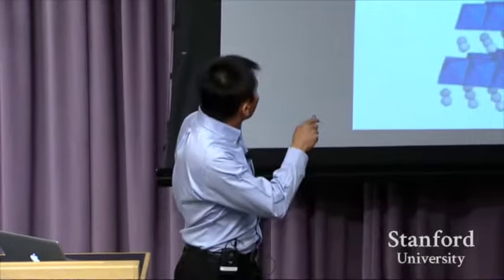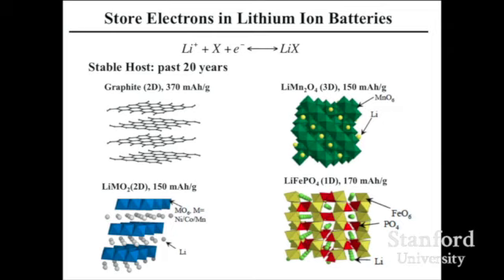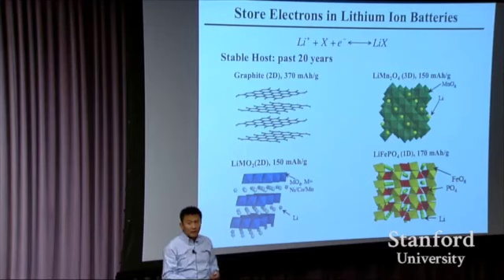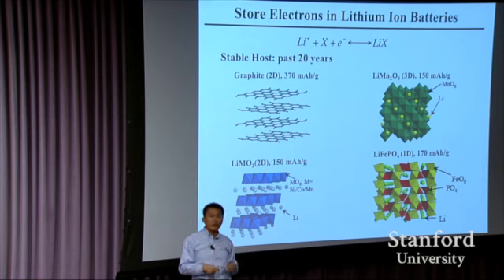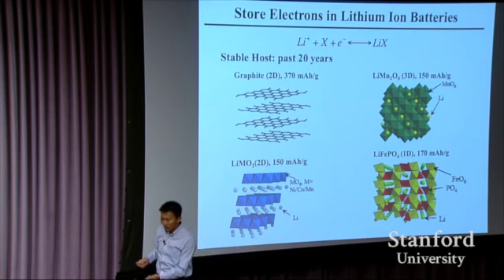So in the past 20 years, this is what we learned. You need to have a stable host for the electrons and the ions. So graphite is for the anode, 370 milliamp-hours per gram. Lithium manganese oxide, layered lithium metal oxide, lithium iron phosphate: more or less 150, 170 milliamp-hours per gram. We can do this back and forth. These two-dimensional, 3D and 1D spaces allow ions to come in, electrons to come in, to meet right there without a big structure change or volume expansion. So you can do this 500 cycles, 1,000 cycles also.